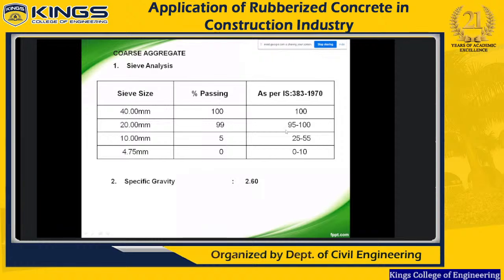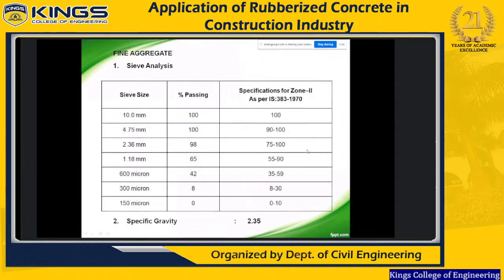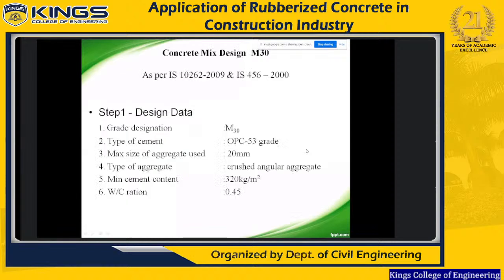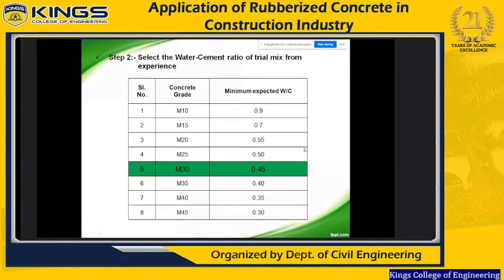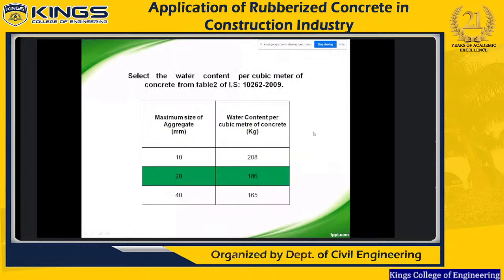Sieve analysis is a simple test; we are aware of it for fine aggregate. So the mix design we arrived at from IS 456:2000, based on the mix design data for M30. We arrived at the mix design based on the water-cement ratio trial mix. So for M30 it is 0.45. We took the water-cement ratio as well as the water content per cubic meter of concrete from the table in IS 10262:2009, with a maximum aggregate size of 20 mm.